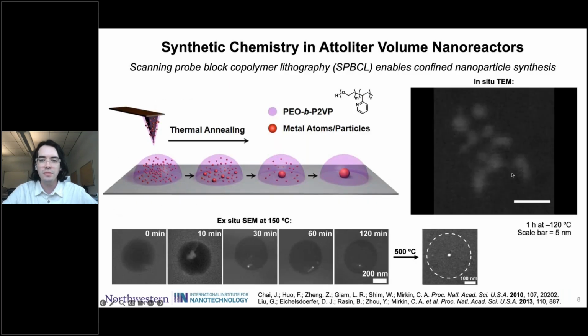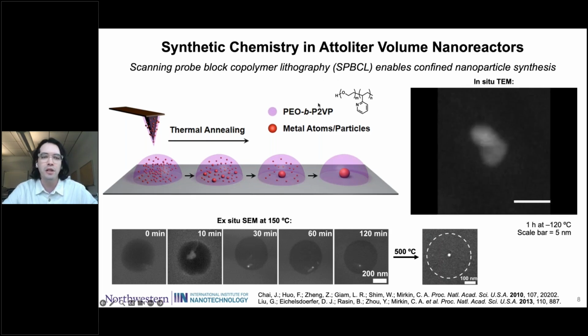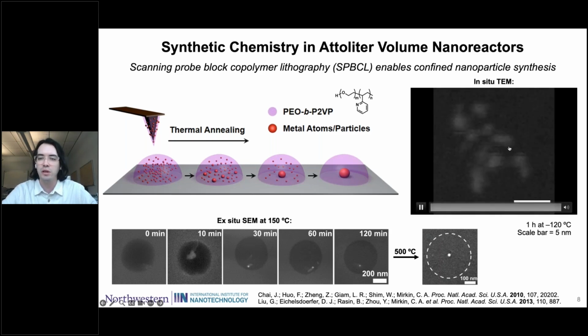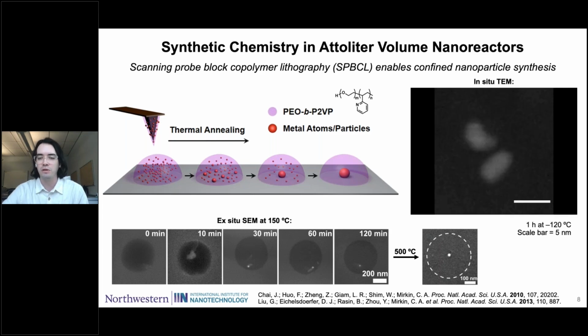Going back to the synthesis that we're doing inside of here, this technique is called scanning probe block copolymer lithography. We're patterning on the surface these droplets, which contain this block copolymer shown here. It has PEG and pyridine moieties on it. In that, we dissolve metal atoms that will use this polymer as the solvent as we heat up the reaction. Over time, the metal atoms will reduce, aggregate, and form a single particle, as you can see in the video of the in situ particle formation.